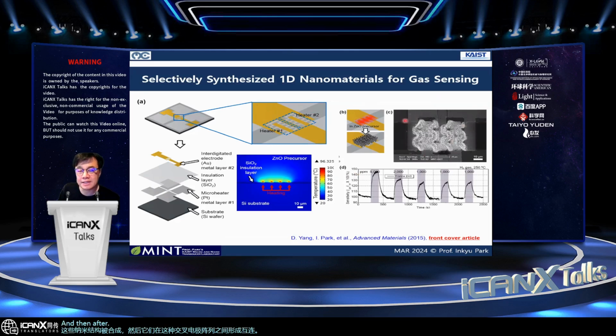And then after this synthesis, we can use the same heater structure not only for the synthesis, but also for the actual operation of the gas sensor. Because for the gas sensor operation of this metal oxide, we need a high temperature. I use this heater, which was originally used for the synthesis, also for heating the sensor for actual gas sensor operation. So we can obtain some gas sensor signals from this platform.